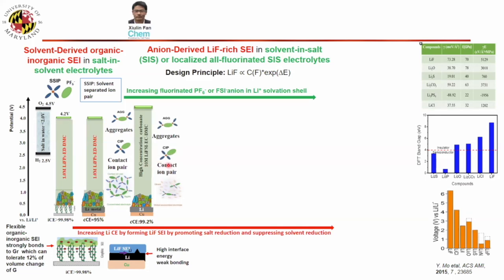PNNL also did a lot of work and called this localized high concentration electrolytes. We did the same thing. We used HFE, diluted high concentration electrolytes. The difference is we use carbonate, because carbonate has a higher reduction potential and also has a chance to be reduced. And then we use a fluorinated carbonate, so even if the solvent is reduced, it still has the opportunity to form lithium fluoride. So we can get the same coulombic efficiency as high concentration, but 99.2 is still too low.